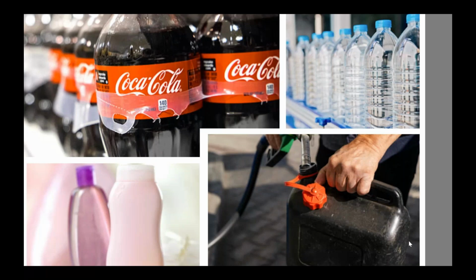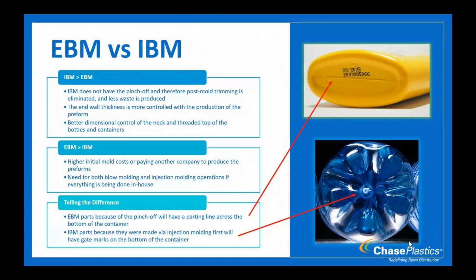Okay, so then we compare them, extrusion blow molding versus injection blow molding. Again, both are good processes, great for making hollow parts, with slight differences. With injection blow molding, you're not going to have the pinch off. The mold doesn't have to pinch around what's extruding out, so you're not going to have that waste, and you don't have to trim it. If it doesn't fall off automatically when it pinches off, you'd have to trim it off. Or even if it does, you still might want to trim it so you don't have any flash left over. All that process is eliminated if you do injection blow molding instead of extrusion blow molding.